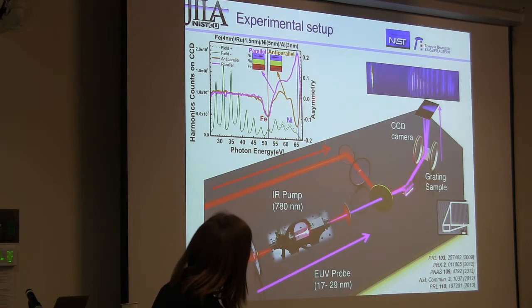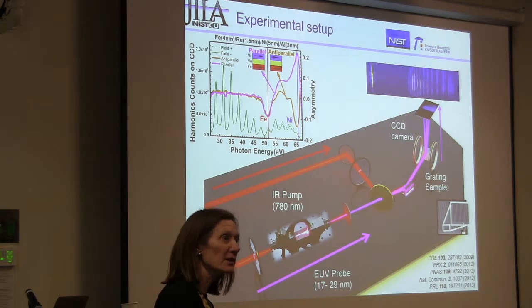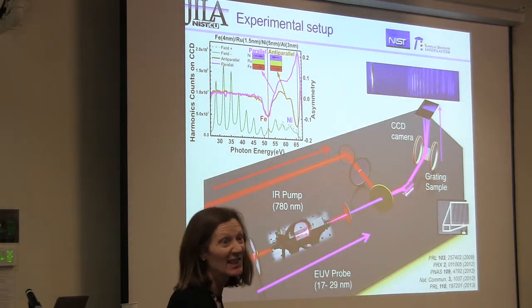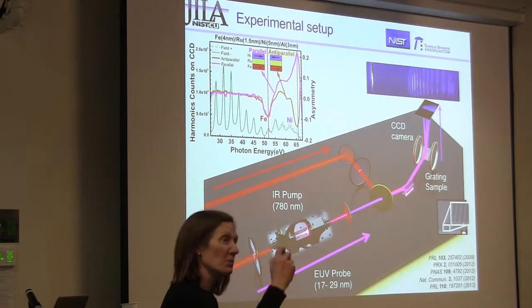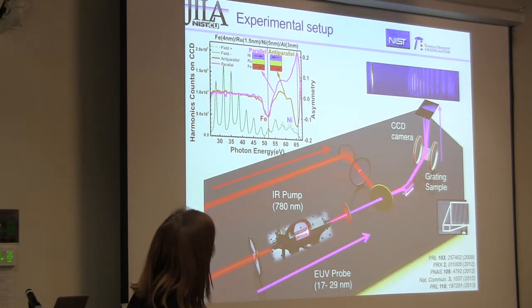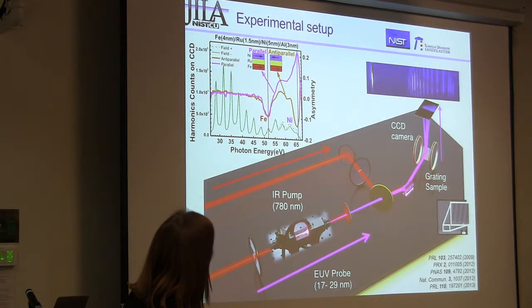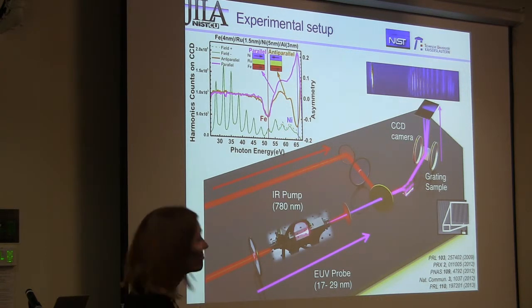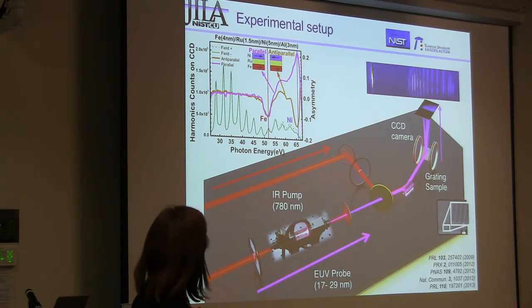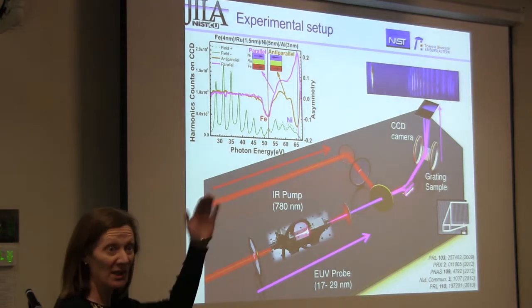It's a huge effect that the reflectivity is dependent on the magnetic state, and you get a huge change in reflection. For example, this is the harmonic spectrum, and the dashed and the solid are the spectrum as we flip the current in the Helmholtz coils. So you can see it by eye. There's a huge change. That's called the magnetic asymmetry: there's a different reflection depending on which way the magnetization in the sample points. The purple curve is the difference between these two signals, normalized, and we call that the normalized magnetic asymmetry. If you heated the material statically, using a heater, then the magnetic moment would be gone, there would be no difference between the two, and this magnetic asymmetry would be flat. So we just look at how the magnetic asymmetry changes.